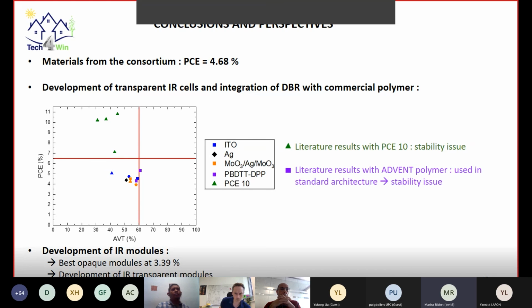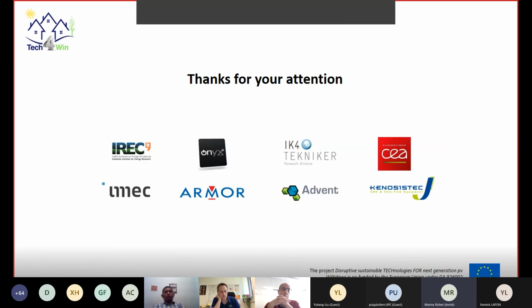But as we can see, there are some stability issues with this polymer, and we don't use it in the project. So if we exclude this result, we can see that our results are comparable with those obtained in the literature, and in particular with those obtained with the ADVENT polymer in the literature. And to finish, we want to develop infrared modules and transparent modules. So thank you for your attention.